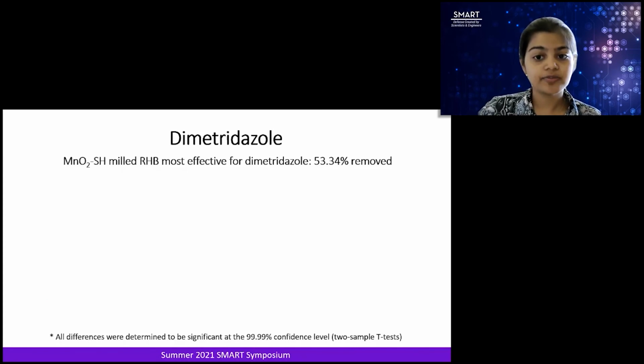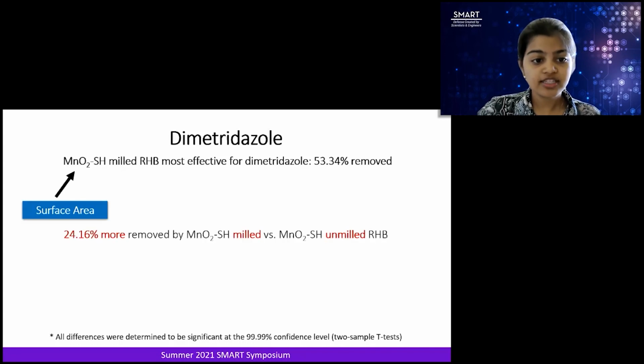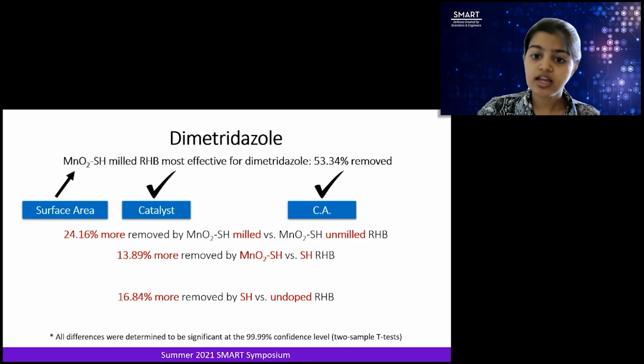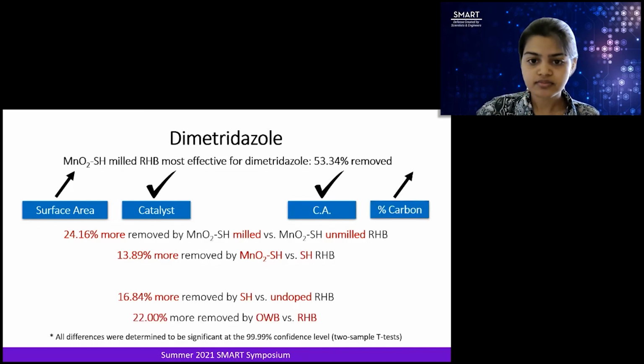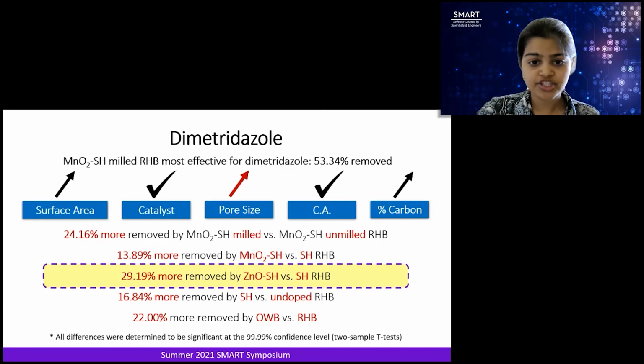Manganese oxide thiol-doped milled rice husk biochar was again the most effective for dimetridazole, removing 53.34% of contaminants. This tells us that high surface area, catalyst presence, a surface complexing agent presence, increased percent carbon composition, and increased pore size are important for the sequestration of antibiotics. Now, this is a little interesting because here, pore size was actually the most important for contaminant sequestration, and 29.19% more dimetridazole was removed by zinc oxide thiol-doped biochar versus just thiol-doped biochar.